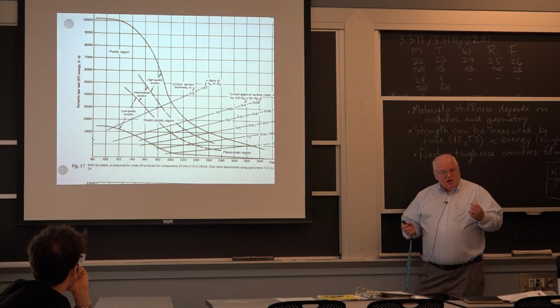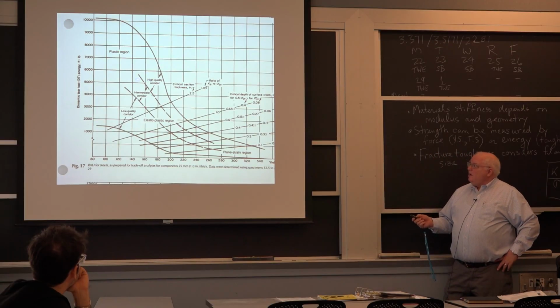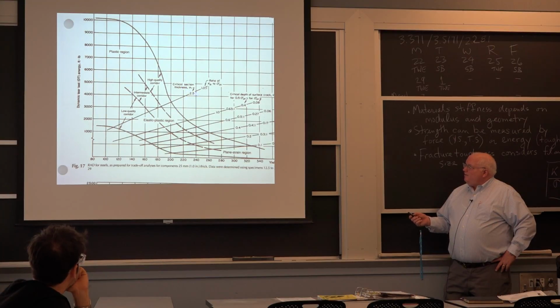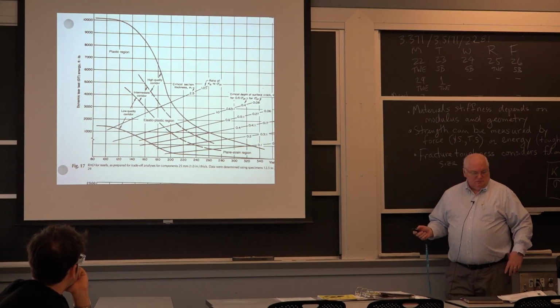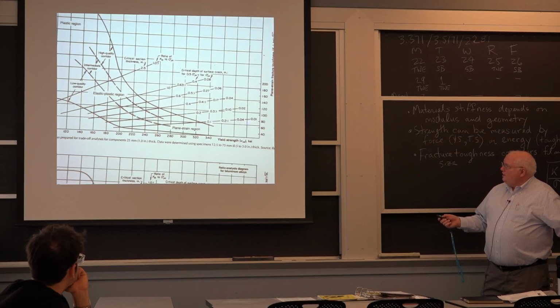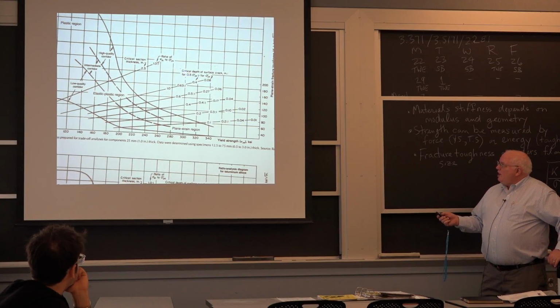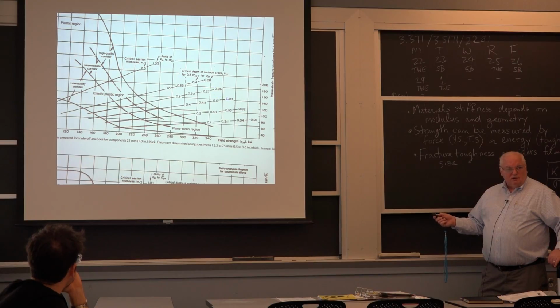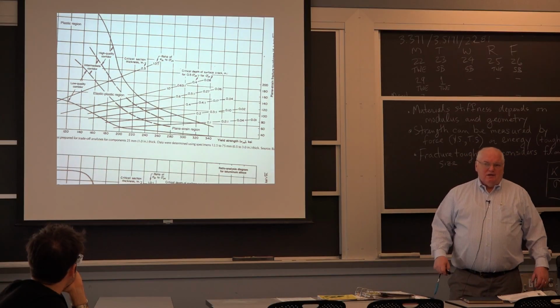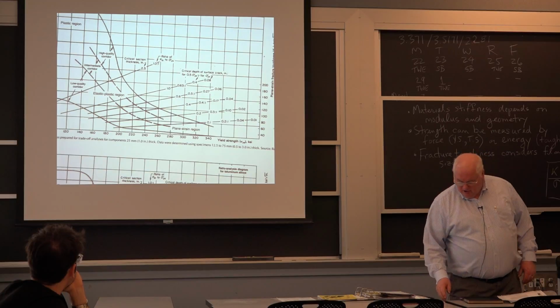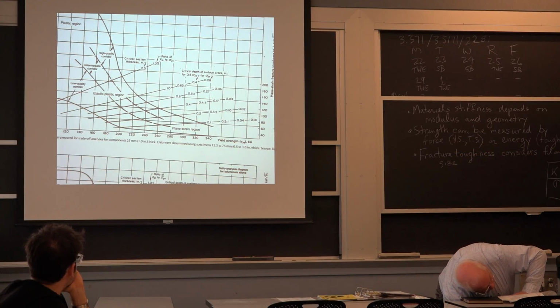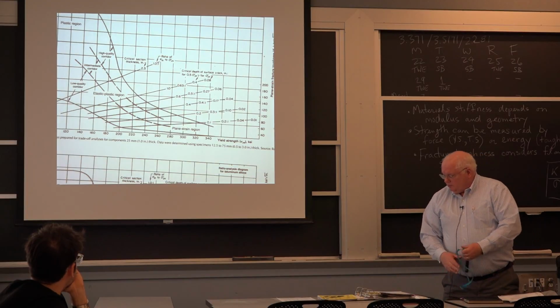Okay, the critical flaw size is not a little 2 millimeter flaw like that brittle piece of stainless steel I passed around. At this strength level, you need a 2.5 inch flaw to have the thing fail in a brittle manner. At a higher strength level, depending on whether the stress you're applying is half of the yield stress or at the yield stress, a 10 mil flaw could cause the thing to fail in a brittle manner. So we're talking about aircraft landing gear. You've got to inspect to 10 mils, 4 human hairs, to make sure the thing is not going to fail in a brittle manner. And it's not a good day if it does fail in a brittle manner.